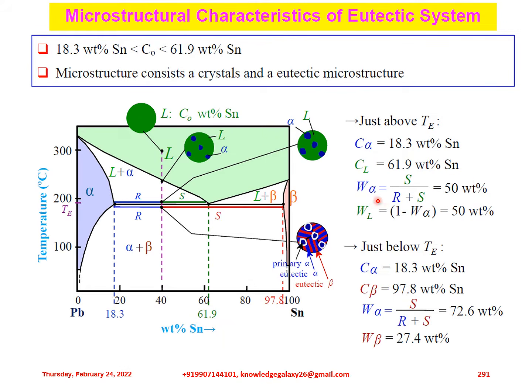So weight of alpha is equal to S divided by R plus S. S is this length, and R plus S is this total length. So it comes to approximately 50%. And weight of liquid is equal to 1 minus weight of alpha, which gives 50%. So this is just above TE, meaning this particular line R and S. It has been marked with different colors to differentiate them.